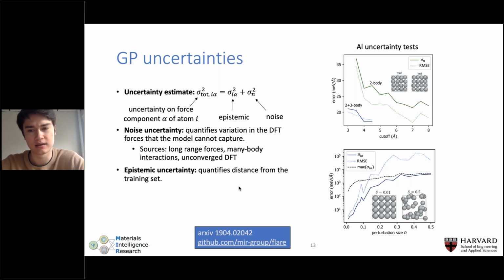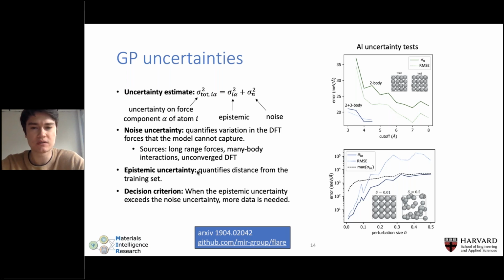So these are the two uncertainties that contribute to the total uncertainty estimate of the Gaussian process. And we can use these two different uncertainties, the noise uncertainty and the epistemic uncertainty, to define a decision criterion about when we need more data. The idea here is that if the epistemic uncertainty starts to dominate, if it goes way above the noise of the model, that's a signal that more data is needed, that you're evaluating the GP on a new structure that isn't going to give very good results. So whenever the epistemic uncertainty goes above the noise, we make a call to DFT, and we update the training set of the model.